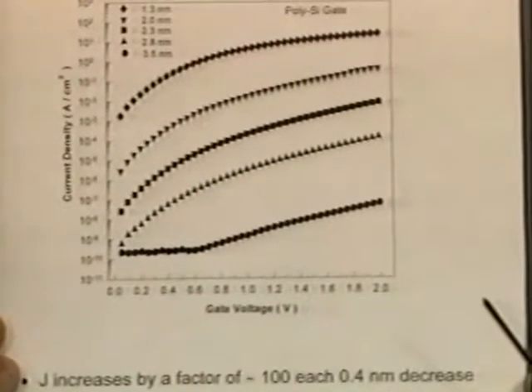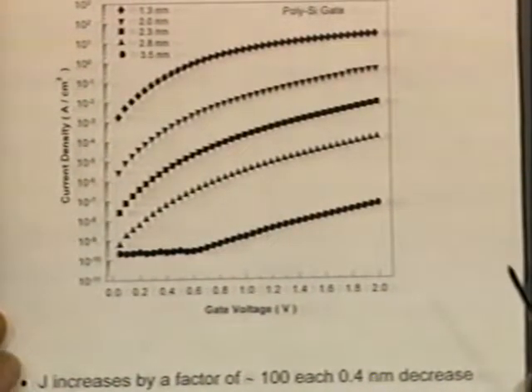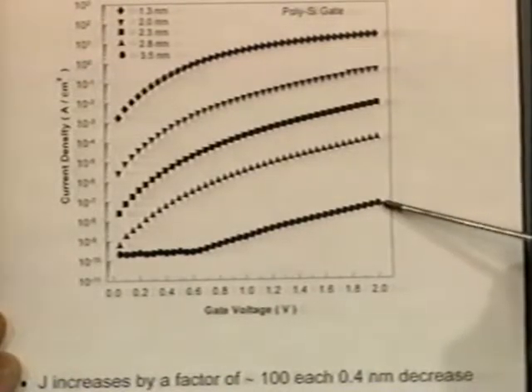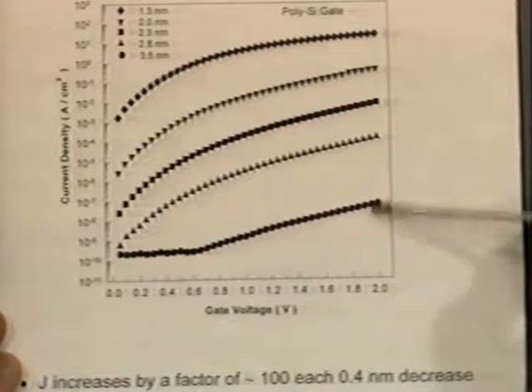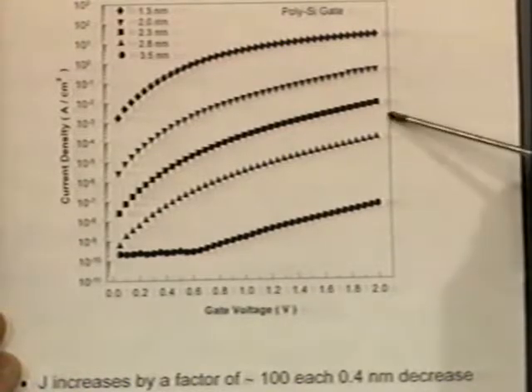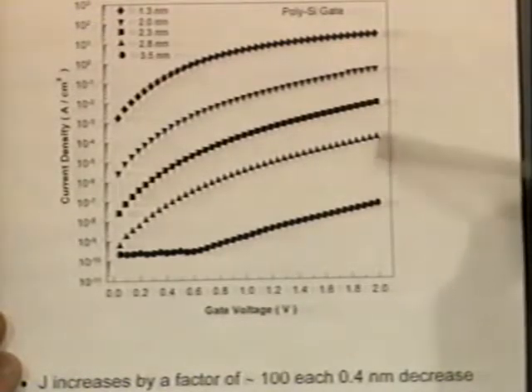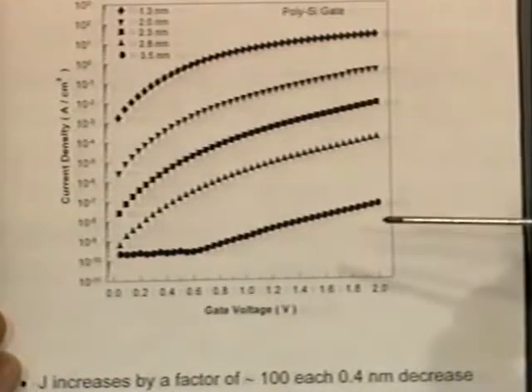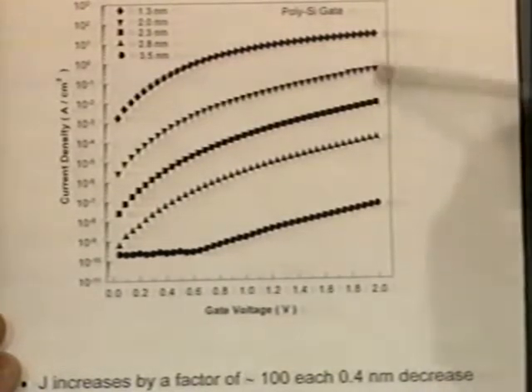And this is the first order approximation of how you characterize the devices. As you say, on average, these oxides are roughly some thickness, and since that's 3 or 4 angstroms, or 2 or 3 orders of magnitude here, that's 3 or 4 angstroms thickness difference. And so roughly speaking, this is a measure of the thickness of the oxide.